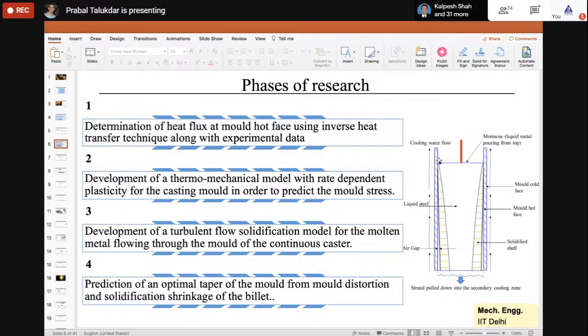So the first thing we have done is that we have found out the heat flux at the interface from the experimental data which has been obtained from industry. So once we have the heat flux profile at the hot boundary of the mold, then we can get the temperature profile, because you can solve the conduction equation for the mold, and then you get a temperature distribution inside the mold. So once you have the temperature distributions, then you can solve a thermomechanical model in order to find out the mechanical stresses, the thermal stresses developed here. So you will be able to do that part, which is not CFD.